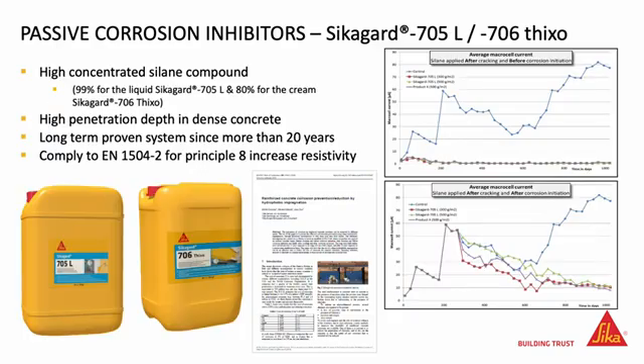These two silane compounds, Sikagard 705 L and Sikagard 706 Thixo, were introduced by Sika in the mid-1990s. Studies and publications in the last 10 years have shown their ability to arrest corrosion in certain conditions — even when the corrosion is already active, as shown in the curve presented in the picture in the bottom right — and to prevent corrosion when the silane is applied on cracked concrete prior to the initiation of corrosion, as shown in the curve in the picture in the top right. Both products comply with the highest requirement of EN 1504 part 2, especially in relation to the control of resistivity.